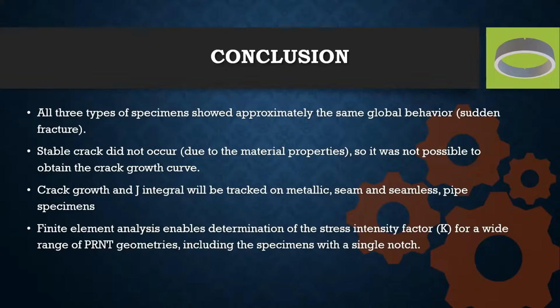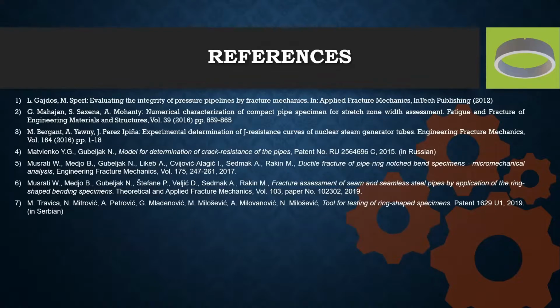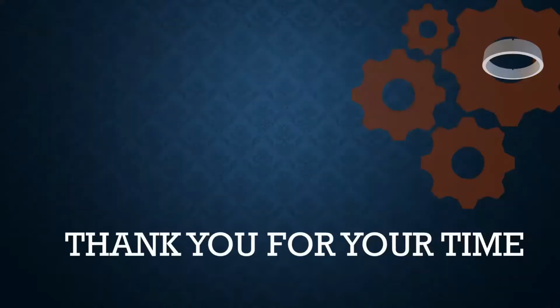Crack growth and J integral will be tracked on metallic, seam and seamless pipe specimens. And the finite element analysis enables determination of the stress intensity factor, K, for a wide range of PRNT geometries, including the specimens with a single notch. Here are the references, and thank you for your time and attention.